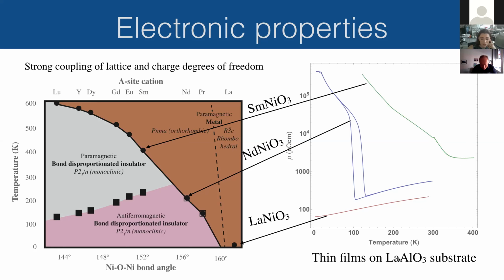Just to note that these are thin films, these plots. All that serves to do is slightly change the transition temperature. So if you're wondering why the points here do not match in temperature with the transitions you see here, that's why. In summary, you have a strong coupling of lattice and charge degrees of freedom in the nickelates, meaning that when you change the A-site cation, you change the bond angle, and you change how stable this insulating phase is.